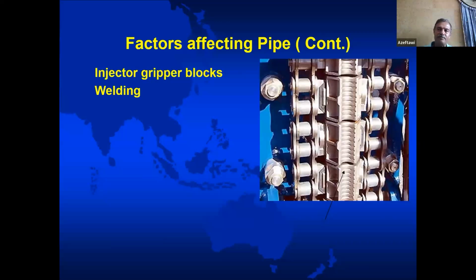And the pipe manufacturer tells you that if you do a butt weld, then you have to degrade my pipe. If the original pipe you purchased has a tensile strength of 100,000, then after you made this, well, it is not 100,000. Go to 90,000. So you degrade your pipe accordingly. If you degrade it with the tensile strength, then you degrade it with everything. All the mechanical properties are degraded.